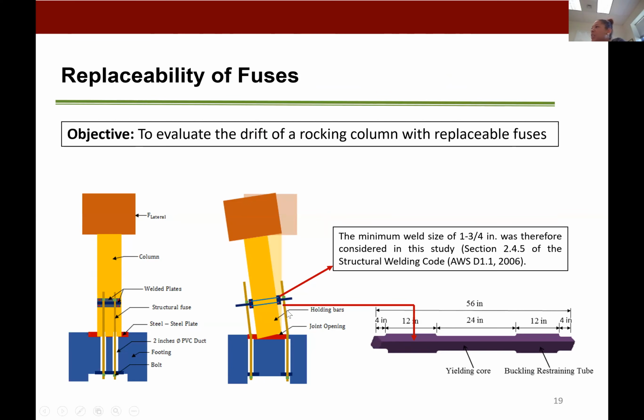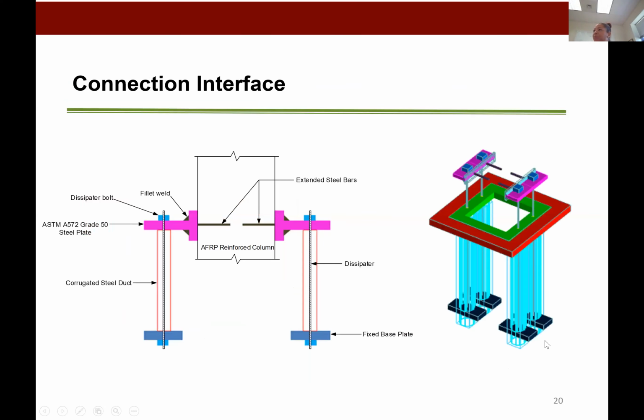So if we look a little bit deeper, we have quite a bit of steel, these 4 bars on the outer perimeter of the column, and essentially have these, you can think of it as a buckling restrained tube with an inner yielding core of about 1/2 inch and an outer core of about 1 inch. If we look a little bit closer at the details, which we are still refining, this is the first pass of the study of looking at the connection interface, where we have the rocking AFRP reinforced columns.